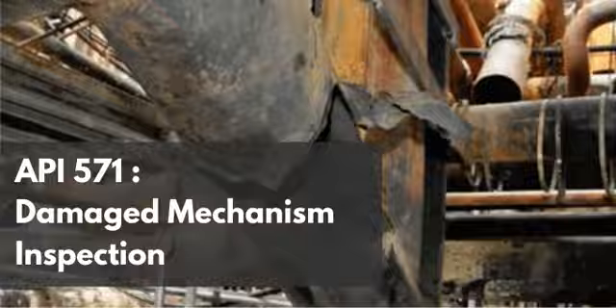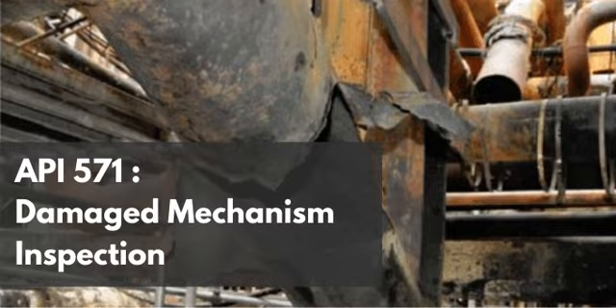But wait, we are talking about steady-state operations here, just running the plant day in and day out. But the data specifically calls out critical process events that take a slow, creeping diffusion and throw it into absolute overdrive. Yes, the process events are the real danger zones. It details that steam and air decoke cycles are highly dangerous. Why? Because temperatures during these decoke cycles often exceed normal operating temperatures, massively accelerating the carburization.